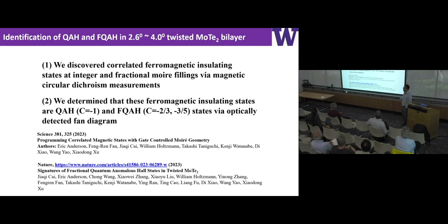The initial twist angle, what we found that's actually working, is random. It's around 3.5 to 4 degrees. But now we've tested a lot more devices, and others in the community have also tested a lot of devices. I think the range we can safely say has these QAH and FQAH states is between 2.6 and 4 degrees. But this range is a dynamic range. I think with more and more devices made, probably the range will also be expanded. But the take-home message is that it's actually not very sensitive to the twist angle if the twist angle is large, okay? But it's not 1.4. It's just a joke. It's not an offensive joke, okay?